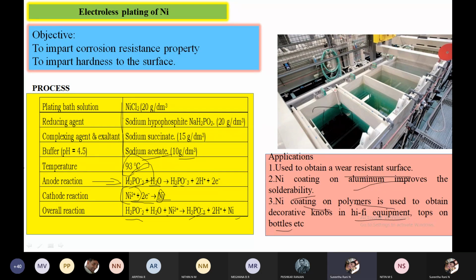Okay, I'll just repeat. What does electroless plating of nickel mean? Electroless plating of nickel is done without using an external power supply. The bath composition is prepared by adding nickel chloride, 20 grams per dm cube. Forget about this quantity; if you can remember, write it. Otherwise, if you write that the bath solution contains nickel chloride, that is more than enough.